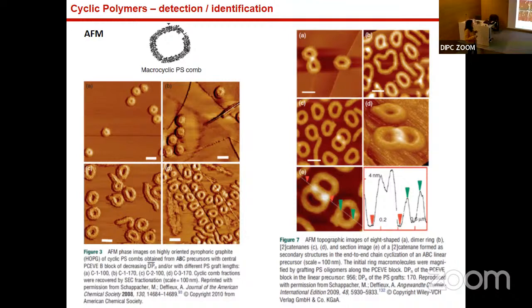And also the size should be perfect to be measured by AFM, to see this hole that the tip can go through these cycles. It's very nice. So you can see also impurities, linear impurities, and in this case, these catenated cyclic polymers that all the physicists ask me about in the talks, because this is very, very nice. But in this case, this is an impurity. To synthesize this kind of catenated cyclic polymers, they have to be synthesized with some specific reactions. Okay.